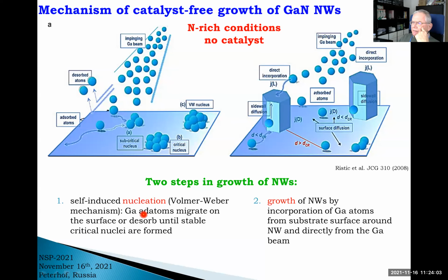Okay, so the process I will be talking about is the following. This is just a sketch. We have MBE, nitrogen-rich condition, no catalyst. We have a substrate. We deliver gallium atoms, and then under nitrogen-rich conditions, gallium flux controls the growth. At the beginning, these gallium atoms just migrate on a surface trying to create a stable nucleus. When a large enough nucleus is formed, it is thermodynamically stable, and I will show you that there is a shape transition from such an island into the nanowires. So actually this proceeds in two steps: nucleation and then growth. And in my talk, I will try to show you that we can have an insight into these processes.